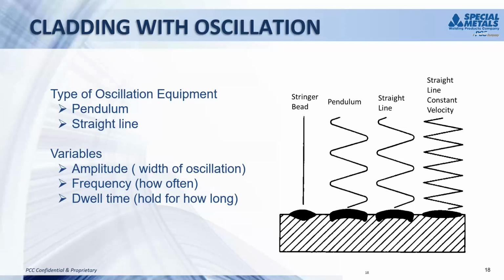The other thing to keep in mind is some of the variables that you can typically always adjust in an oscillation. You can adjust the ends of that weld, whether you're trying to minimize one side versus the other, to put a little bit more metal where you don't have a bead versus the side that you're tying into. And again, there's no right or wrong process. Just be aware of the differences and the nuances and make sure you're applying the best type of oscillation for what you're trying to do.